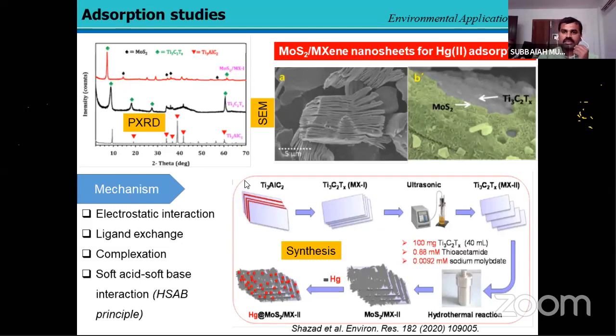Then we can see some images. You can see the crystalline form of MXene. Then after coating with the molybdenum sulfide, it has both the layers above as well as the basal plane, the interlayer surface.